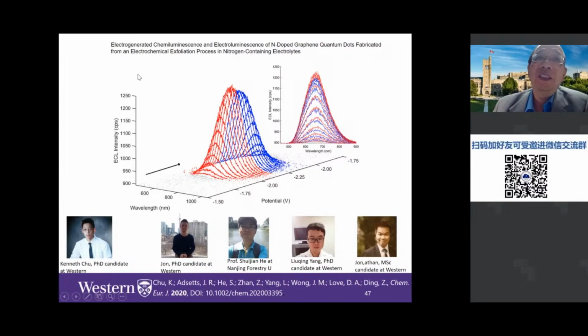So we do the electrochemiluminescence of these graphene quantum dots, and in fact it's nitrogen doped, and we can get this kind of spectrum. Nice. It's strong. However, we did notice that these graphene quantum dots give you the ECL peak around 600 something. And I emphasize that with the photoluminescence, it's blue. So similar to the silicon quantum dots, we can just give different stimuli, then we can get different responses from these smart materials.